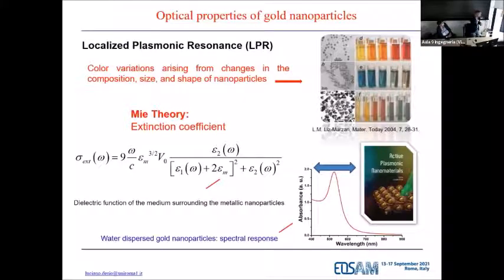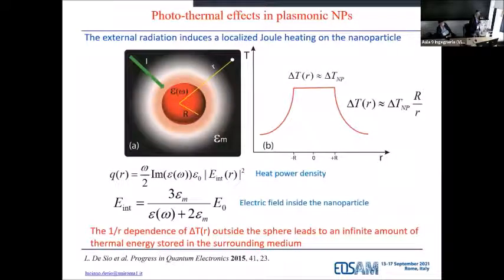But remarkably, there is a very nice parameter, which is the dielectric function of the surrounding medium, namely the refractive index. You change locally the refractive index, and this will change the coloration of gold nanoparticles. You do so, you can control very easily the coloration, the plasmonic band of gold nanoparticles by acting on the surrounding medium. Associated to these very intrinsic optical properties of gold nanoparticles, there is a strong temperature increase nearby the particle due to the absorption, essentially.